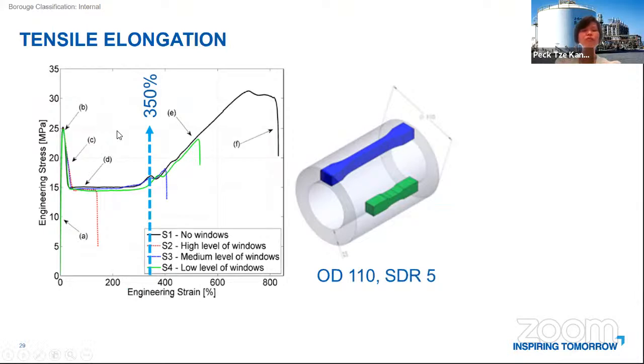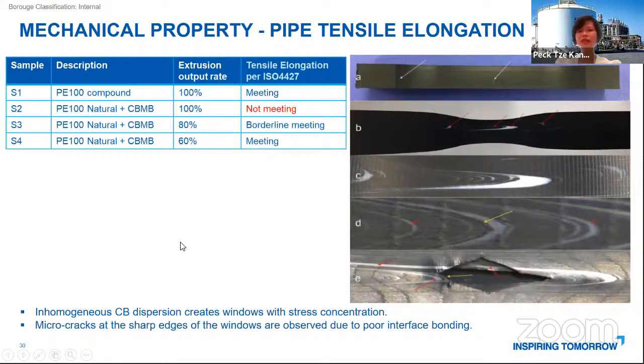What about the tensile performance of such a system? We did samples 1, 2, 3, 4. We cut the dog bones from the pipes and did a tensile test. According to standards, by performing a tensile test on the dog bone taken from a pipe, they should surpass 350% elongation. But in this case, we find that sample 2, which we tried to run at the same extrusion rate as a normal system, could not meet it at all. So are the other 3 and 4; we actually need to drop the output quite a lot in order to fulfill these tensile requirements. So why is this happening?